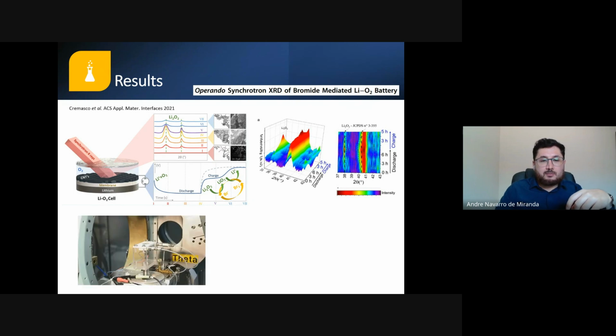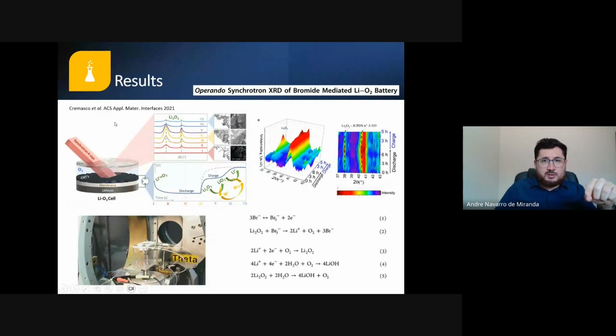So this is the experimental setup of this. It was not in Sirius, it was in the last accelerator. And then we can understand better the mechanisms here of the bromide and the formation of the peroxide. And then we also saw here the formation of a little bit of lithium, I always forget this name, hydroxide. And it's mostly because of a little bit of water in the system. So we need to avoid water as well. So this was a really nice experiment that we have done in 2021.